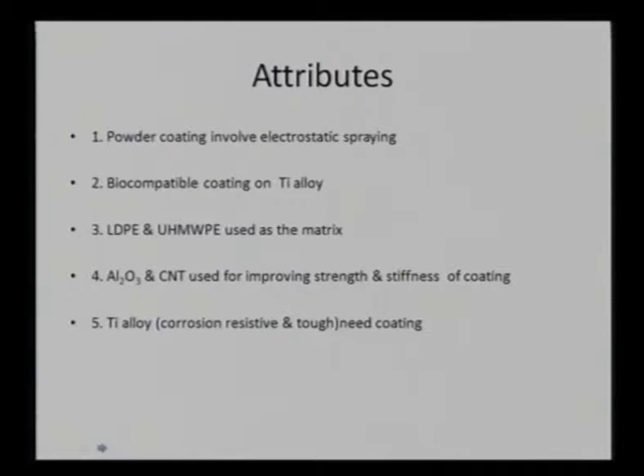And if these coatings have to be utilized as superior coatings, much more superior in terms of the mechanical and tribological properties, they also have to retain the cytocompatibility at the same time. Only then can we extend them to certain potential biomedical applications. So there are certain attributes to it. First of all, we are utilizing electrostatic spraying for the powder coating. Secondly, we know that they need some charge for the surface so that they can dissipate their charge. So for that, we need to have a metallic entity where the charges can be taken away. That is nothing but a metallic substrate, which can be titanium alloy, stainless steel, or cobalt chromium alloys. The only required criterion is that the substrate has to be conducting in nature.